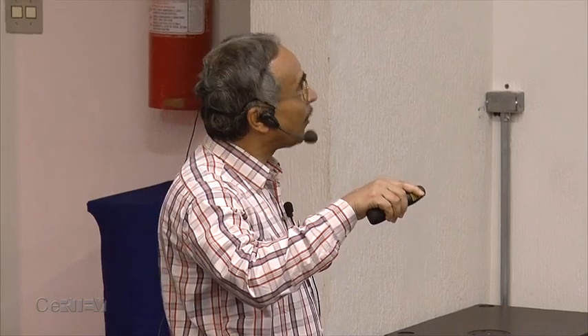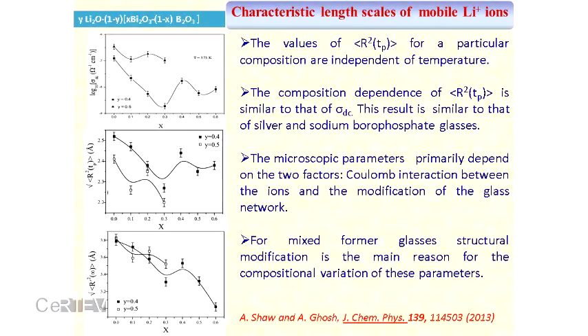So the structural units, which are very important to describe this type of material, are also important for the ionic conduction in glasses. We have also compared our results with the NMR measurements. Here one group measured the same thing using NMR, but their composition range is limited. They observed the same maxima at the same compositions we have observed. So our results are also very similar to the NMR results. So we can get the same information from infrared spectra as you can get from the NMR spectra. In terms of NMR, they are the connectivity between phosphorus and boron, or lithium and boron. We can get the same thing from this infrared spectra.